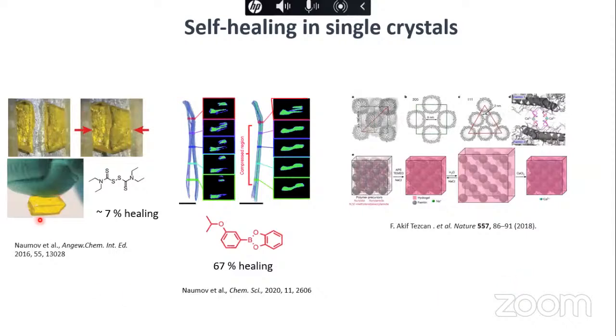For example, this is an example where you cut the crystal and then put it together for almost 24 hours under some small mechanical compression. Then these crystals actually hold on to each other. And as you can see here, this is hanging. So the crystal can actually hold the other piece. Here, the strength that it regains after 24 hours is around 7%. So they call it 7% healing. And this is the molecule.